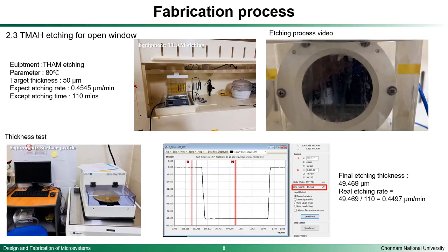After 110 minutes of etching, we use the surface profiler to test the thickness of the open window. And the final etching thickness is 49.469 microns, so it is very close to our target thickness, which is 50 microns.